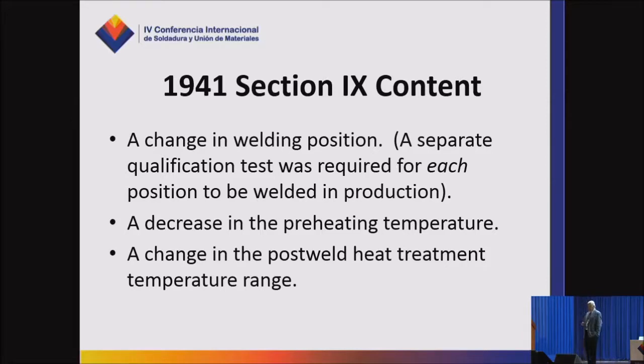A decrease in preheat temperature, similar to what we have today, although today the welding procedure can go 55 degrees C lower than what was used on the test piece. A change in the post-weld heat treatment temperature range. That's pretty tight. Today we have much more open requirements for qualifying procedures with post-weld heat treatment.